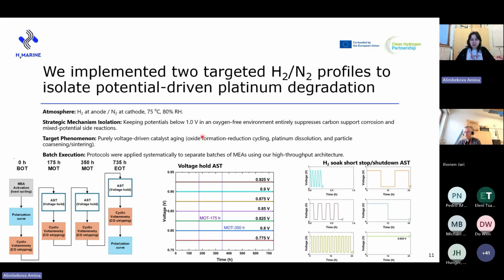The results from the voltage hold AST give us a suggestion for the upper potential limit that is used for the next cycle, which is the hydrogen soak, short stop, and shutdown ASTs, which are meant to simulate the frequent short operational stops and the automated shutdowns that occur less frequently throughout the maritime system lifetime. This is to capture the rapid potential excursions or transients that the catalyst experiences during the short stops or shutdowns. And we were running these protocols and the approximate sequences shown here in the flowchart.